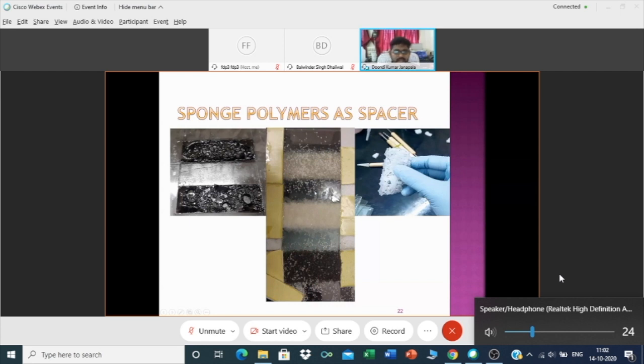How we clean it: after baking at a high temperature, the sugar particles start melting. Then I put it on a magnetic stirrer with temperature control. You set the temperature to 100, put a beaker of water on top of it, put these samples inside, add the magnet, and keep it rotating. You do this for 1 day, and the sugar particles slowly dissolve into the water and it gets clear. That is how you get the sponge with the holes.